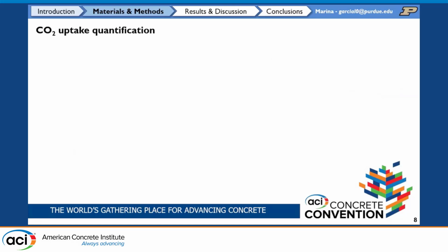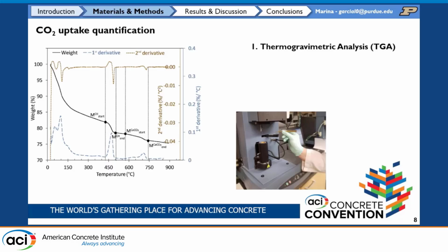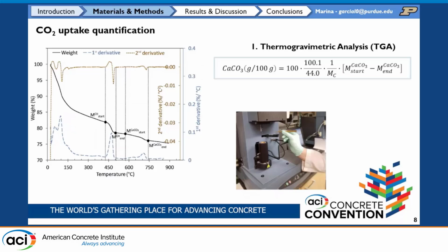So in terms of the CO2 uptake quantification, there are a few methods to do so. One of them is the thermogravimetric analysis, or TGA, in which we measure the weight of the sample that you're testing while you're increasing the temperature. Therefore, if you know the temperatures or the range of temperatures where your compounds will decompose, you can calculate how much of that compound you have in your sample. So in terms of the calcium carbonate, which is the compound resulting from the carbonation, you can quantify how much that is, and therefore, comparing that to the sample that has not been exposed to CO2, you can estimate how much CO2 has been uptaken in that reaction.